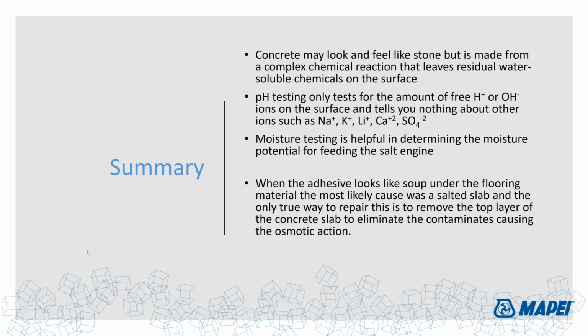So the unreacted cement left in the mix is going to continue to pull moisture out of the concrete slab. It will have a negative impact on some of the values, probably more so on the RH than on the rate of evaporation. The rate numbers, in my opinion, are very indicative of the water to cement ratio. The higher the water to cement ratio, the more water you put into the mix, the more porous it's going to be. So it's like opening the valve up on the evaporation rate machine. If you have big gaps and big holes and a lot of surface area, it's going to evaporate a lot faster than a tighter concrete slab.